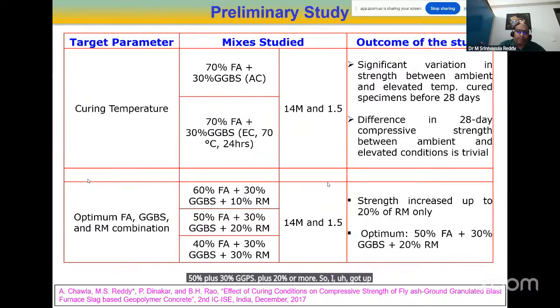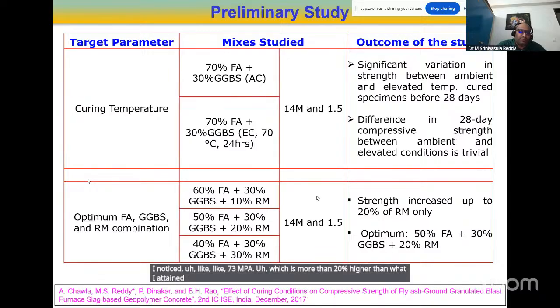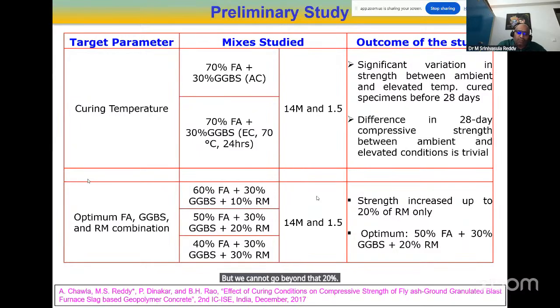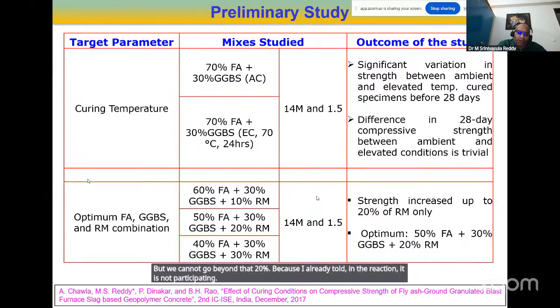So I got up to 73 MPa for the ratio of 0.4, that is binder solids to AS ratio. Sorry, AS to BS ratio. No, I'm talking in the reverse way. So alkaline solution to binder solids ratio of 0.4. If we compare fly ash and GGBS of 70-30 with fly ash, GGBS and red mud of 50-30-20, I noticed 73 MPa, which is more than 20% higher than what I attained for fly ash GGBS alone. But we cannot go beyond that 20%, because, as I already told, in the reaction it is not participating. It will act as a filler only.